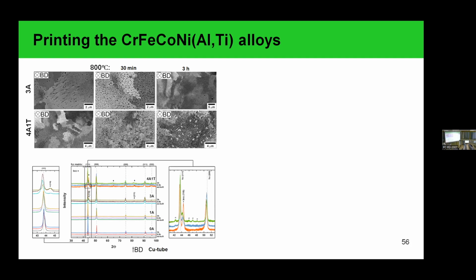X-ray diffraction analysis demonstrated that in case of the small aluminum addition, no changes are observed in comparison with the four-component system. If we add higher aluminum content at the as-built state, there are small percents of a new phase, but not really with big volume, and this secondary phase stabilized during the heat treatment. But in case of the materials with titanium, we observe the formation of a new phase, in high volume, even at the as-built state. And with further heat treatment, we also observed formation of a new phase, which was recognized as the sigma phase.